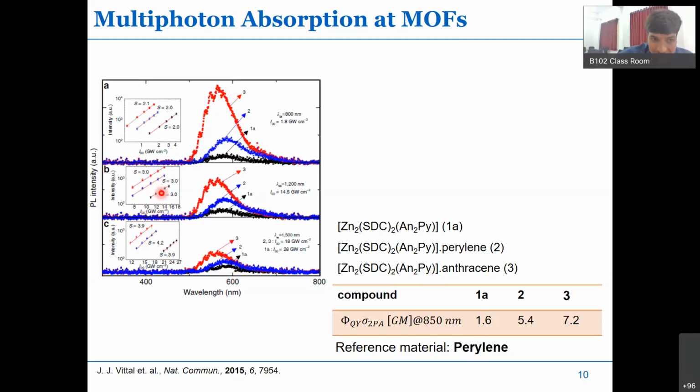It is very easy. So you plot a graph between the logarithm of power versus the logarithm of intensity. Then you see the slope of this at different powers, and if you start observing the intensity of the fluorescence, then you start seeing linear plots, and the slope gives you the number of photons involved in the process.